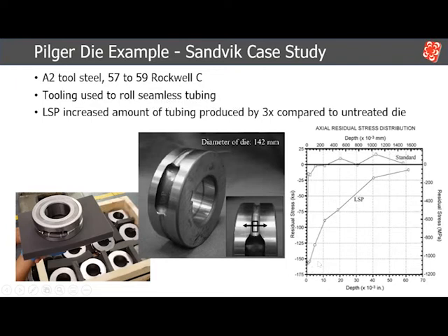In a similar concept, laser peening of dies, which are a very high strength material, generates really high compressive stresses. These high compressive stresses counteract the stresses experienced by these dies, improving their life by 3 times. Something worth noting here, the best benefit is not just the fatigue life of these dies, but the fact that if one of these dies fails, you have to restack the entire rack of dies, meaning they have to take everything out and then reassemble, which adds a lot of maintenance time and downtime for processing.